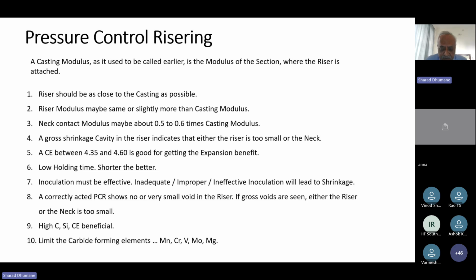They were using the best inoculant. They were using an inoculant feeder, which was attached to their pouring station. So with all that in place, still they were getting a high amount of carbides in their casting. And when we took action, the action was that the inoculation feeder was delayed by a couple of seconds. So it was feeding inoculant into the metal a bit late, and then the initial metal was not collecting inoculant, and it was not really giving the benefit of inoculation.